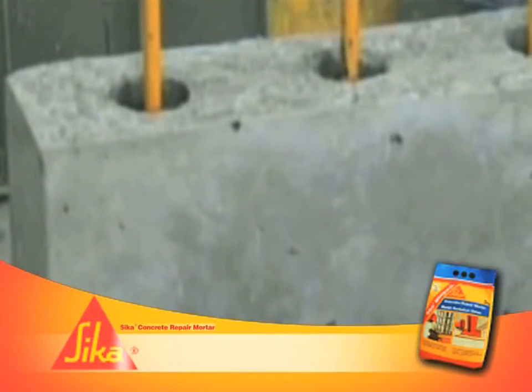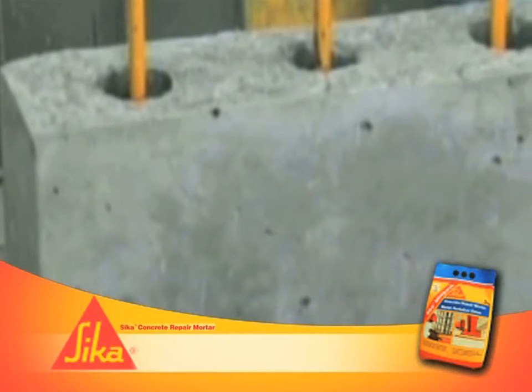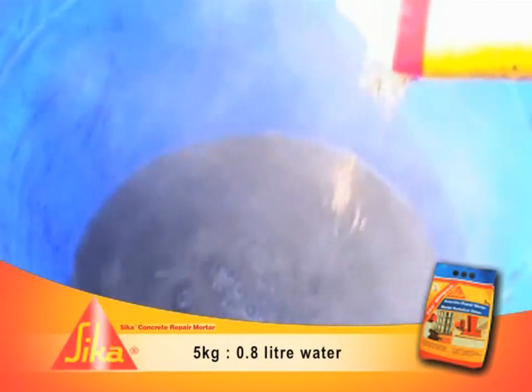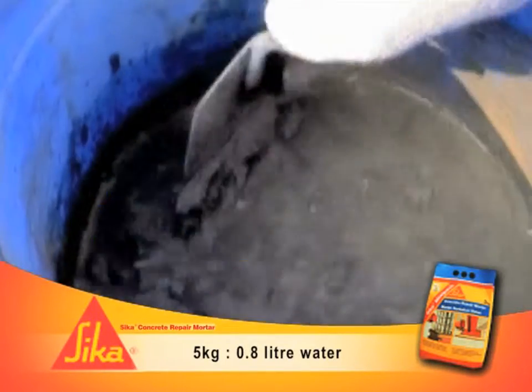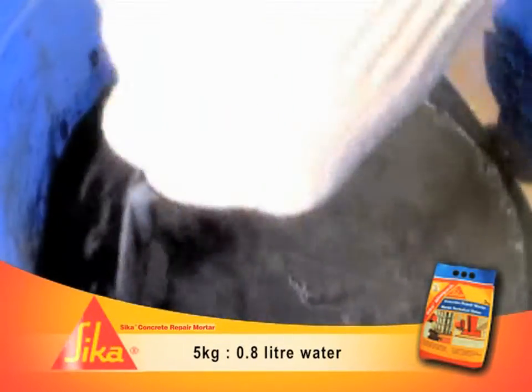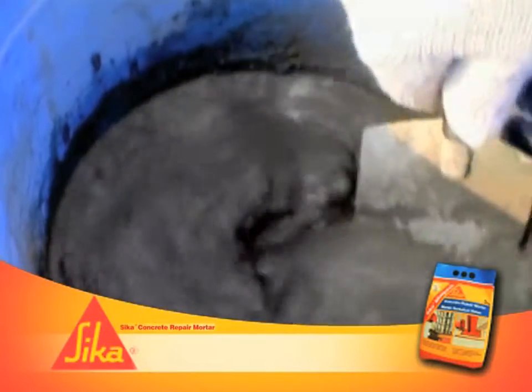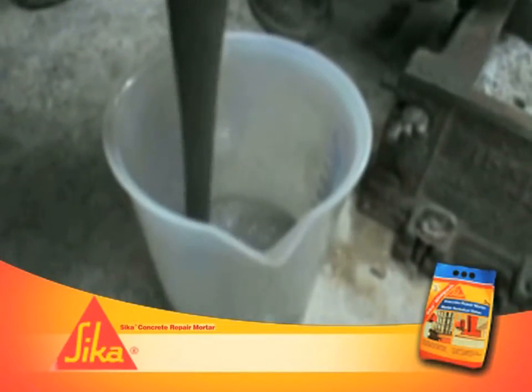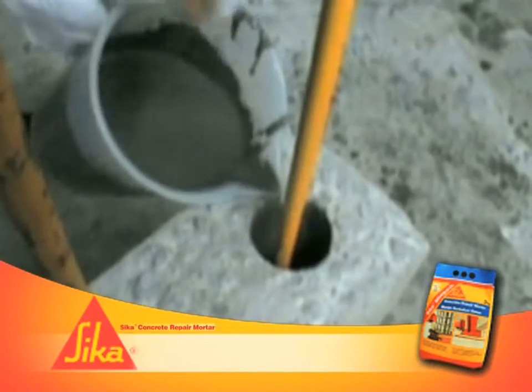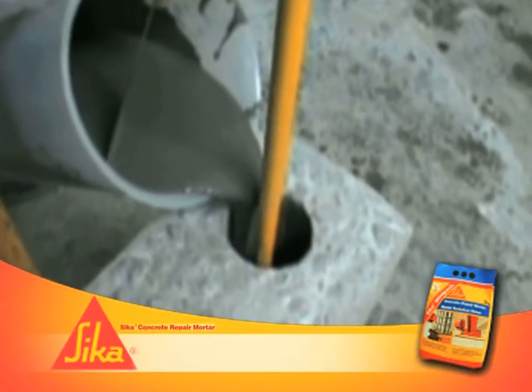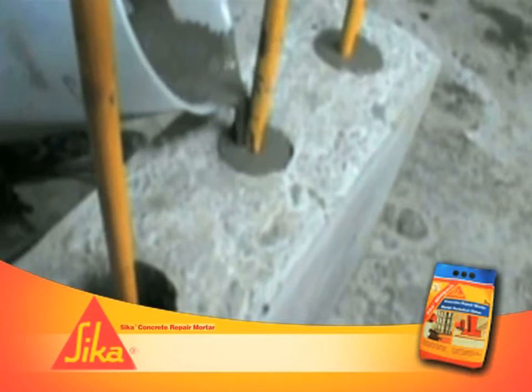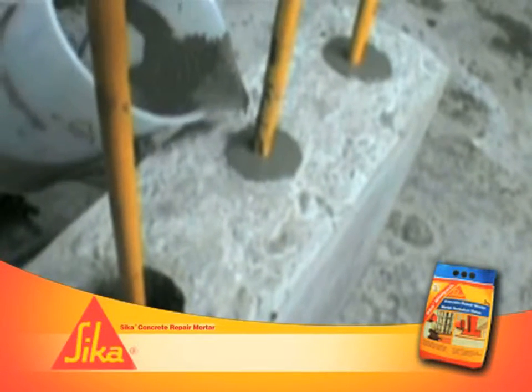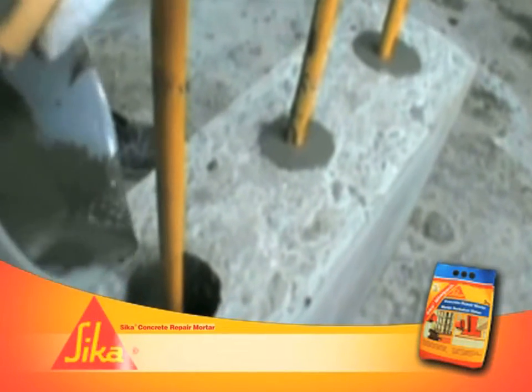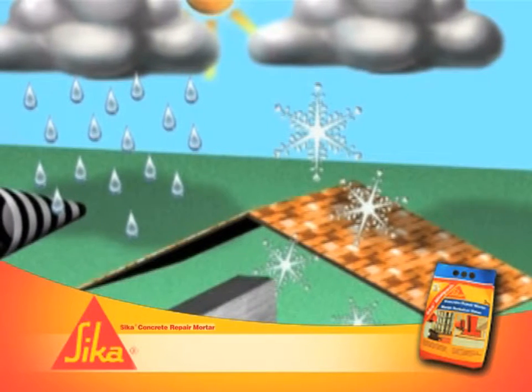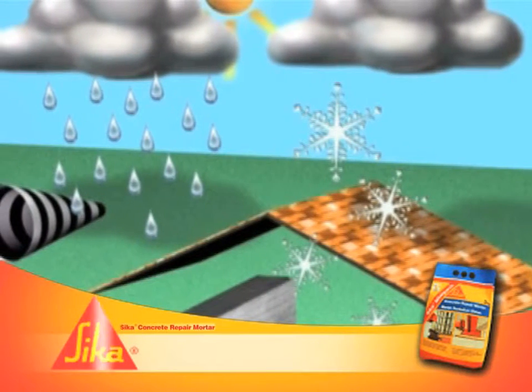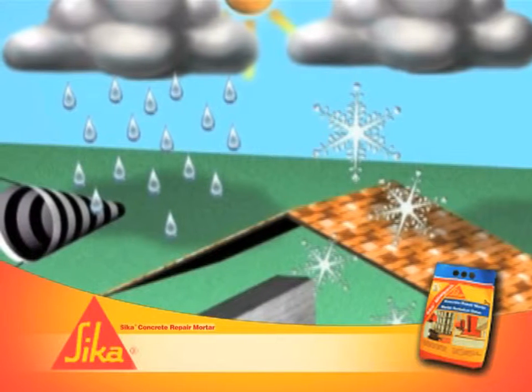Clean the surface from dirt, dust, etc., and pre-wet with water. Add the mortar slowly with water at a ratio of 5 kilograms of mortar with 0.8 liters of water and mix continuously to achieve an even consistency. Pour the mixture onto the cavities, gaps, or grouting for precast concrete sections. For porous concrete, prepare a supporting formwork. During the drying process, protect the surface from rain and direct sunlight.